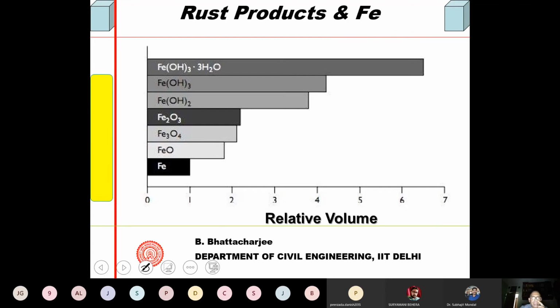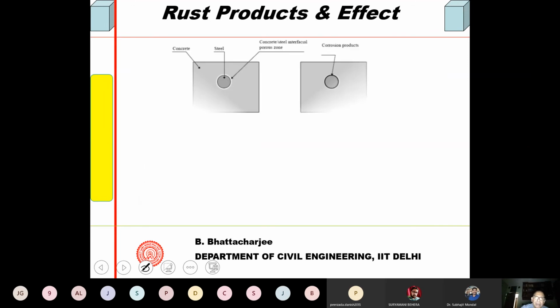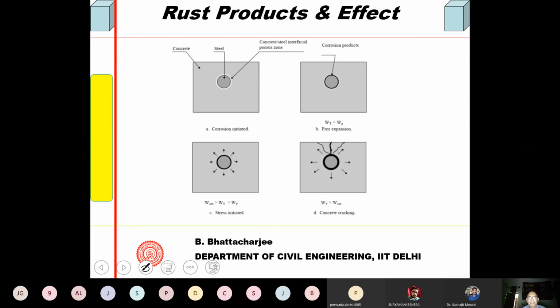So, as you can see, Fe(OH)3 occupies maximum volume, relative volume. FeO is this much, Fe3O4. These are unstable. If the pH is low, it can go to this. If chloride is high, it can go to this. And that's why low pH after carbonation creates problem. High chloride, this creates problem. And what happens? This is what will happen. The expansion will occur. Initially, rust product will form. Then it will start exerting pressure and cracks will come.